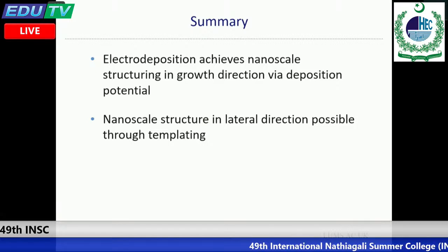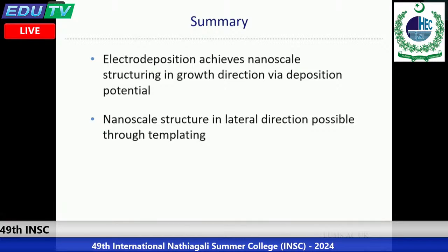Now, that's a really interesting question. The concentration of the electrolyte will mainly affect the mass transport, but our experiments show that the most important parameter for the metals we look at is actually the deposition potential. So for example, if you want to use a very large negative potential, then you've got a problem, because you will also start to deposit the material very quickly, and you will start to deplete the electrolyte.